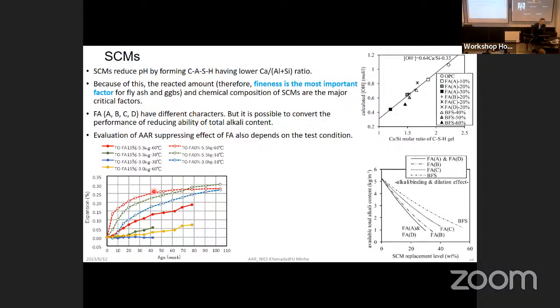Yes, it just depends on the chemical composition of the glass. Some soda glass is not good for it because soda glass contains a significant amount of sodium. By exchanging sodium with calcium, that happens in the cement paste, that results in more alkali metals in the pore solution. That may accelerate the reaction. But glass from volcanic glass, you can use. That's a natural pozzolan, kind of. So artificial glass from some bottles will be dangerous.